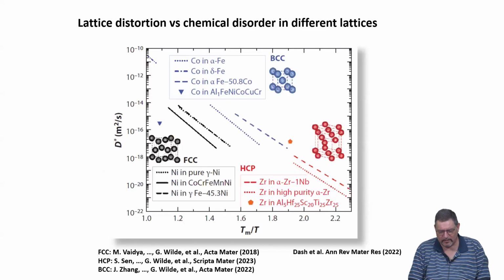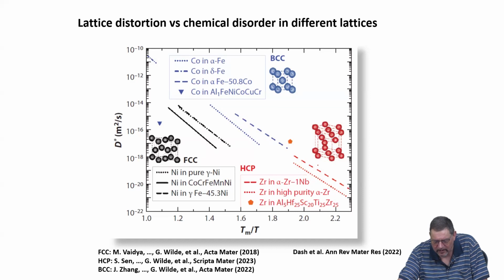So when we look now at lattice distortions versus chemical disorder in different lattices, we have FCC, BCC, HCP now for a comparison. We can see nickel in pure nickel, nickel in the high entropy Cantor, and nickel in a binary system. There might be some sluggishness, but it's not much. But also, when we look, for example, here in the HCP system or in the BCC system, we see a little bit larger variations.